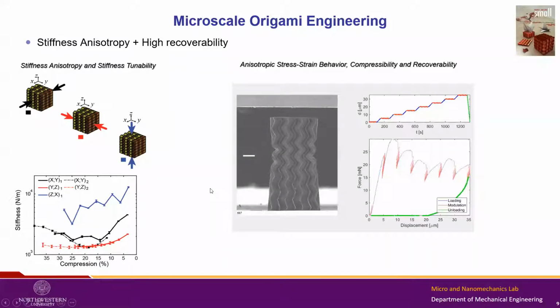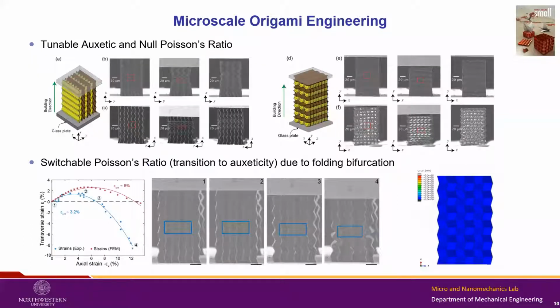As you have probably seen in this video, there's an interesting auxetic effect, and that's one of the other interesting aspects of these structures, which is that they have a tunable Poisson's ratio, which changes with compression, just like the stiffness. And depending on the direction that you're looking at the same structure, you can have auxetic behavior or almost zero Poisson's ratio. Here, to the left, you can see that when I'm looking at this structure from one side, we have auxeticity, and when we look at it from the other side, there's practically zero Poisson's ratio. And the same thing happens with a different morphology of the structure.